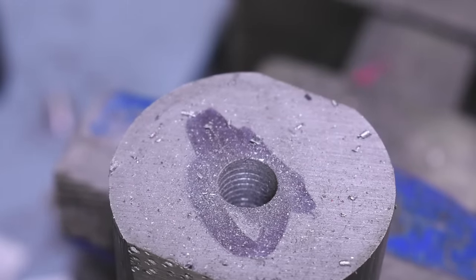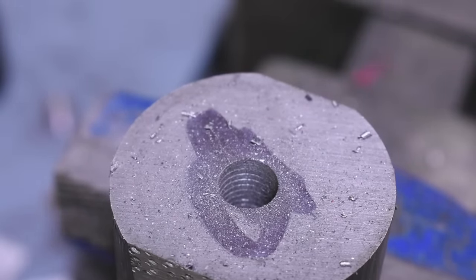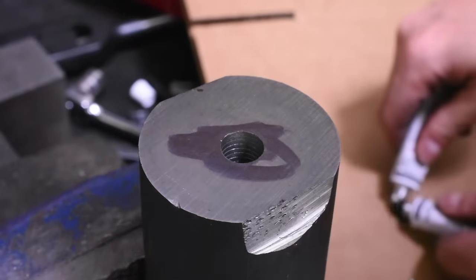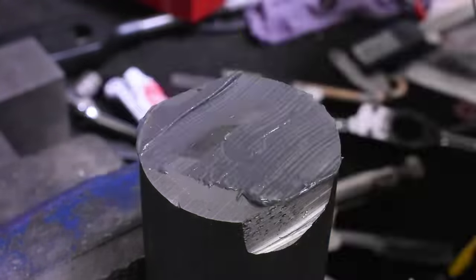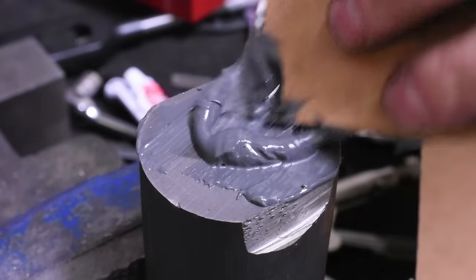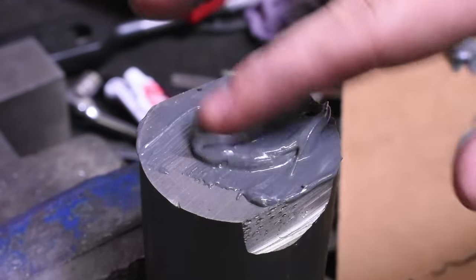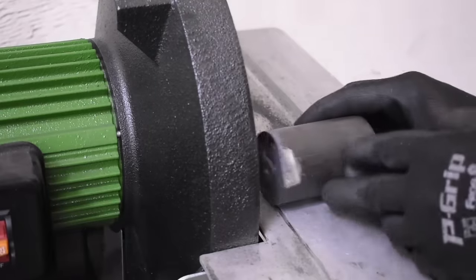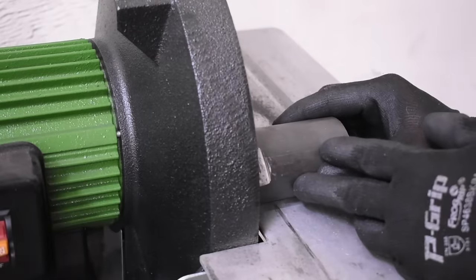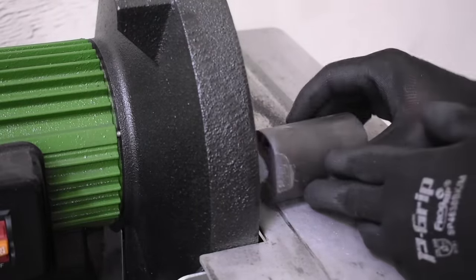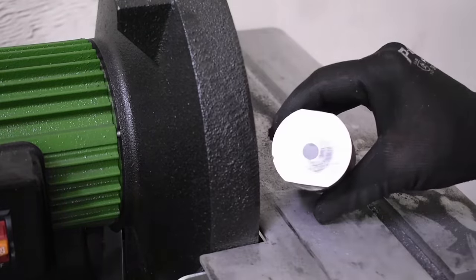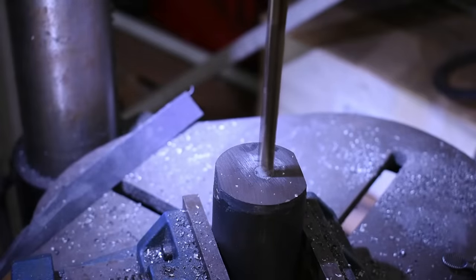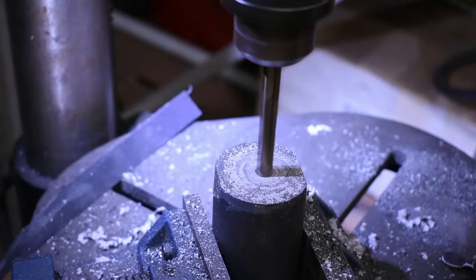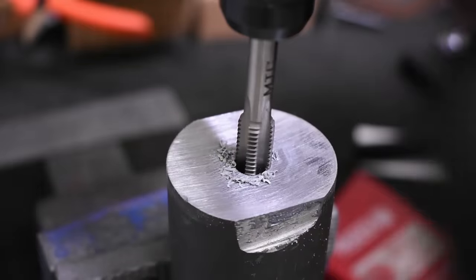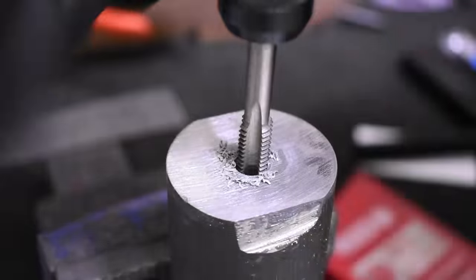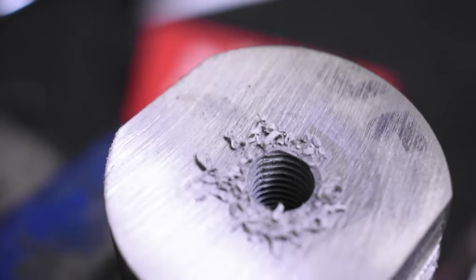So drilling out the threads until they are just basically all gone, leaving the slightest spiral in there for the JB Weld to hold on to, slathering a bunch of the good stuff in there and waiting 24 hours. This isn't JB Quick, you know, for best results. And let's see what it can do. So grinding away the excess, then drilling a new hole with just the JB Weld left to tap threads into. It's not a natural feeling, very gummy, and the result is less than stellar looking, but surprisingly, feels pretty solid.